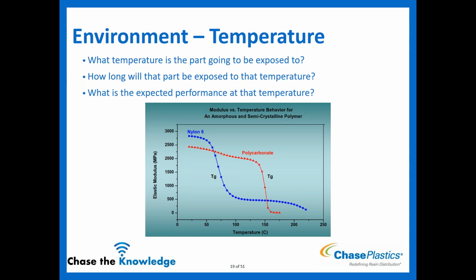So some questions that you might see come up when you're talking about exposure temperatures. The first one would be, is the part going to be exposed to an elevated temperature, or maybe it's a cold temperature, maybe it's outside and it needs to see -40 C? How long are you going to be exposed to that temperature? It's one thing to say that I need a material that resists this temperature. Okay, is it seeing it for 10 minutes, so it's more of just a peak where it might see that for a little bit? Or am I going to see that temperature for 5,000 hours, and I need it to be more of a continuous use type temperature for 5,000 hours?